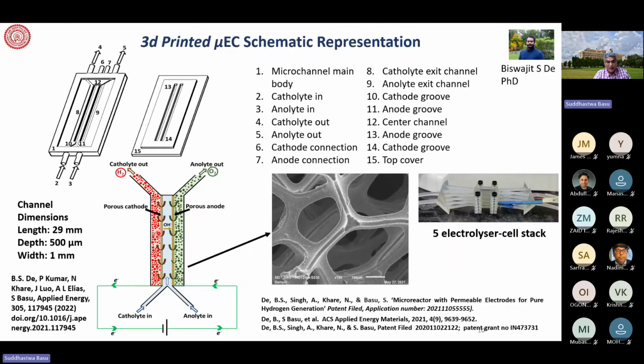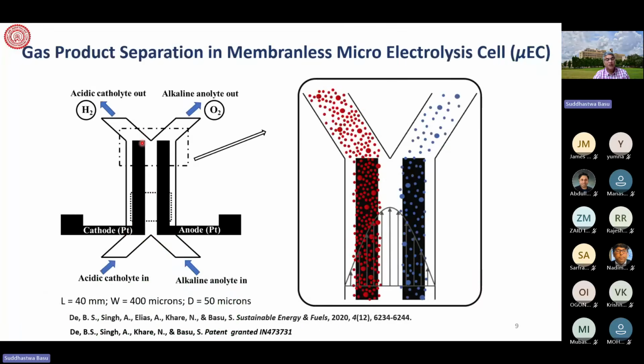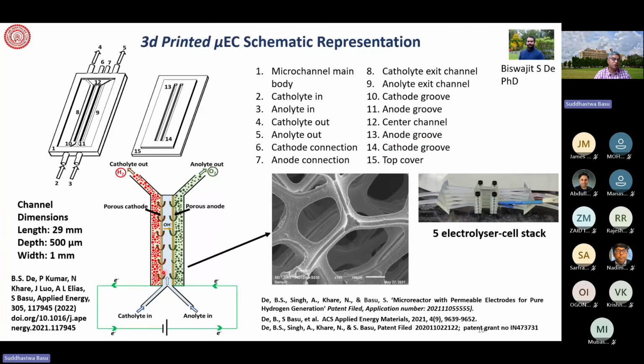We have not changed much in the design here. We just use asymmetric electrolyte, but here we have changed the design and made it much more robust, so it does not allow intermixing of oxygen and hydrogen to take place. What is this design? We have a middle channel which is blocked, and we have porous electrodes, as shown here. These porous electrodes are doped with or spotted with the active material, could be platinum, could be phosphonates, and the water is forced through this middle channel, but it is blocked, with nowhere to go. It can go to the right hand side and left hand side through this porous structure.